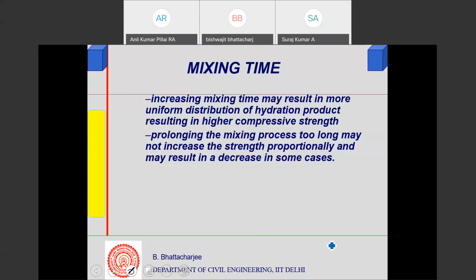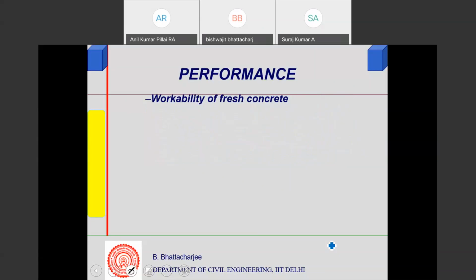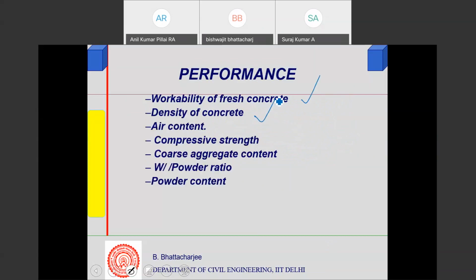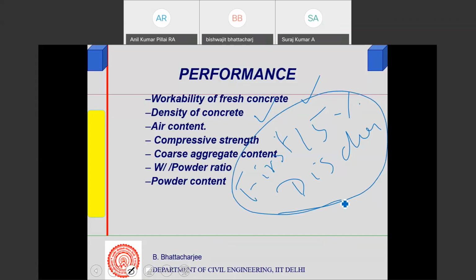Air content, segregation, water-cement ratio, and cement content. Now, take 15% of the discharge, the first 15%. When the machine is discharging, take samples and measure their workability immediately, of course, wet measure, air content. Compressive strength will require time.